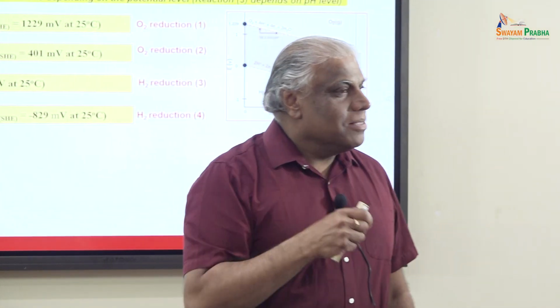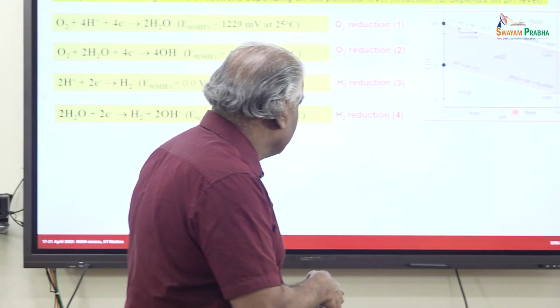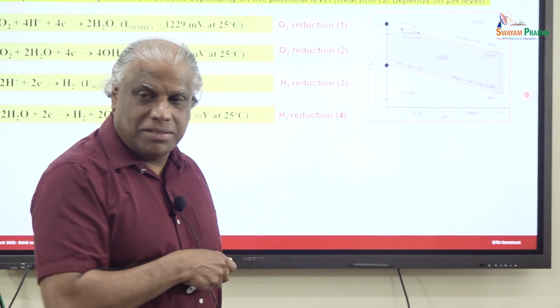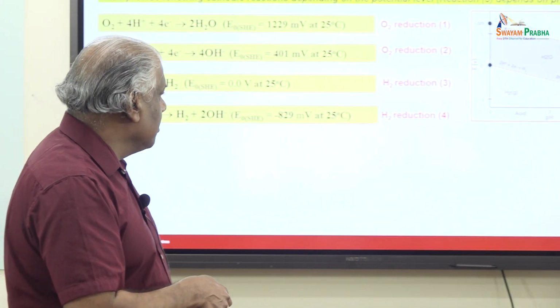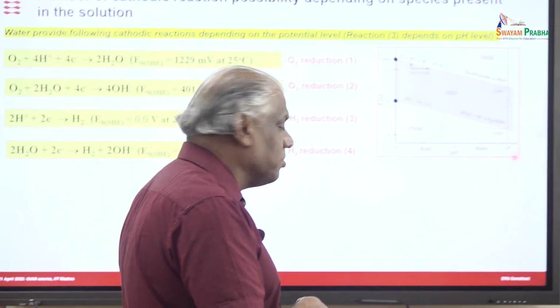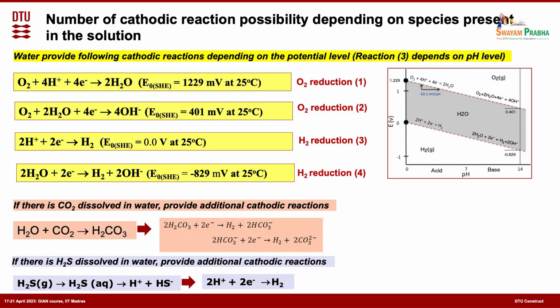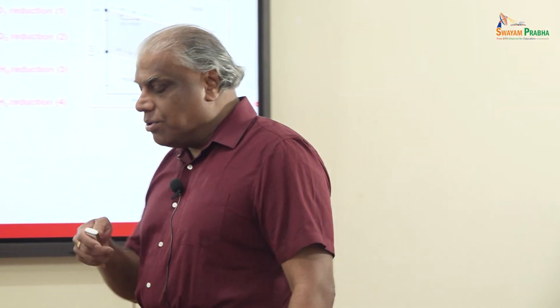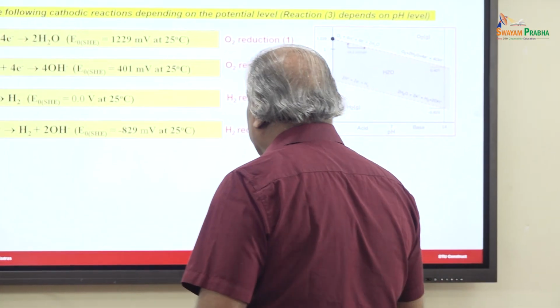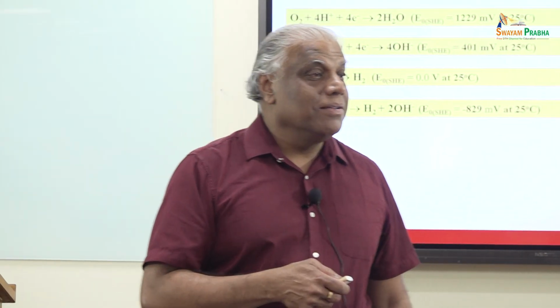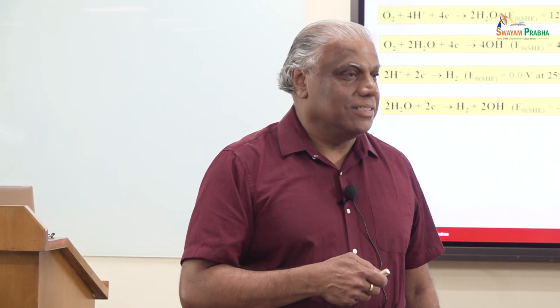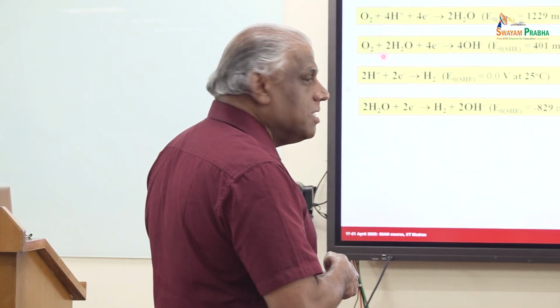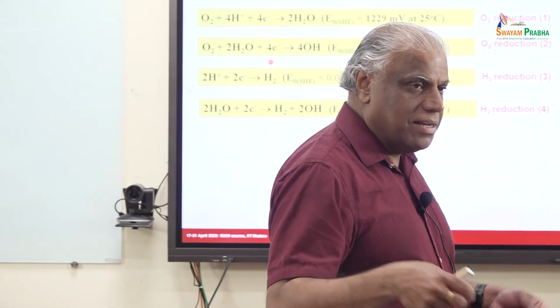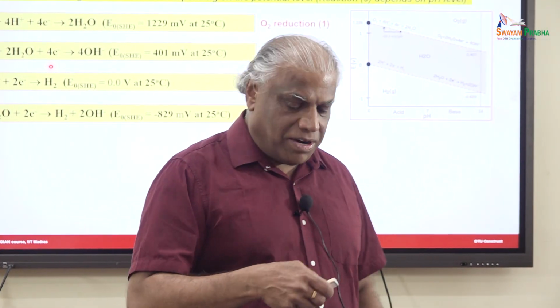Most of the corroding systems are around neutral pH conditions, around this area. Not in alkaline or acidic conditions. If you take seawater, it has a pH close to 7. Similarly, if you look at the fluids used in different applications, like heat exchangers, you have a pH close to 7. So most of the corroding solutions are around 7. The amount of hydrogen ions in the solution is significantly lower, so that shouldn't be the dominating cathode reaction. The dominating cathode reaction will be oxygen, which is dissolved. If you take water, there is some dissolved oxygen, and the dissolved oxygen in the water can be used to produce these reactions.